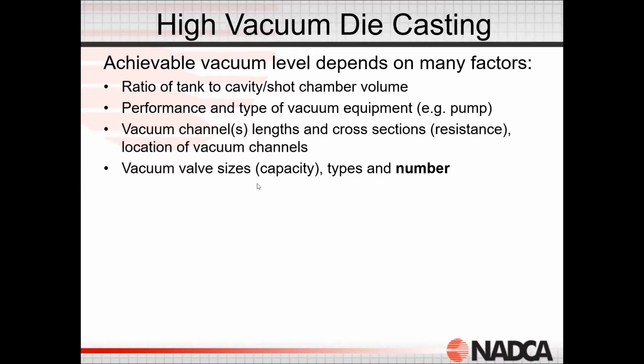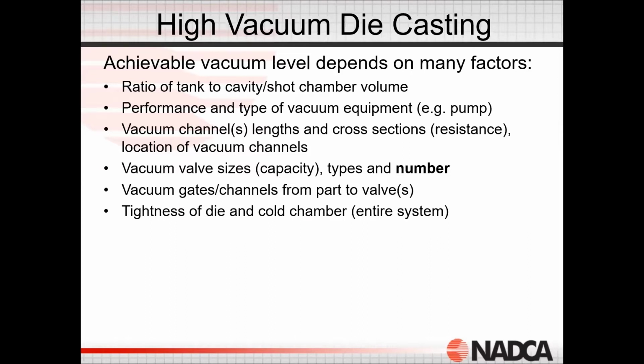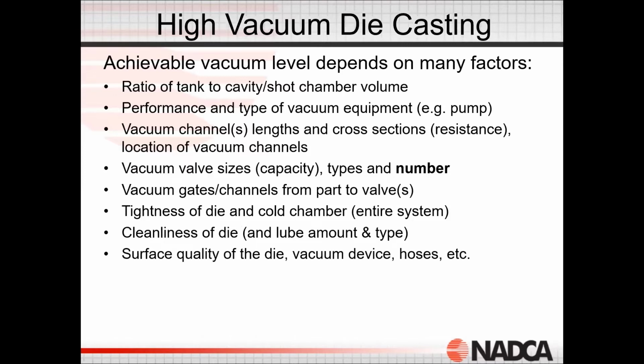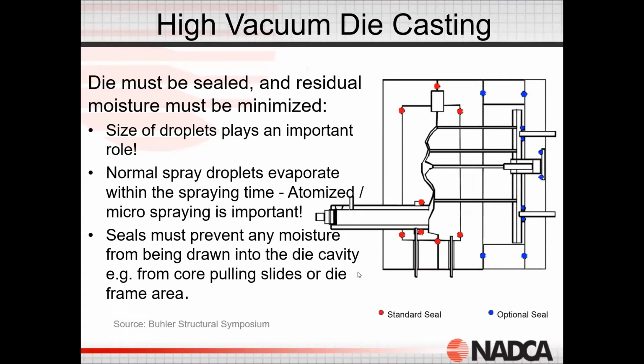So we've got to have vacuum systems, runners, lengths, vacuum valves, all capable of removing that air, removing it very rapidly while we're filling the casting to make sure that we have a very tight process. And we then also have the entire tool sealed. The tool has to be clean. It can't have any die lube or any excess liquid inside the machine while we're making the die casting. So this is the moisture in the die. And when we're controlling that moisture, we have the tool completely sealed.